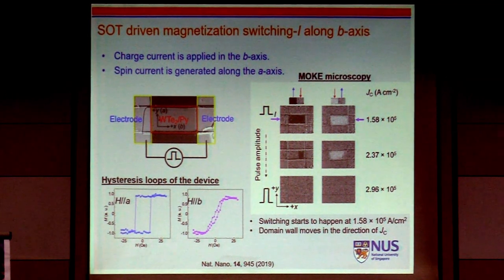And this material is very anisotropic. Depending on the current injection direction, whether you are injecting along the A or B, you can see quite different behaviors. This is an example with current along the B direction, and then we can polarize our spin along the A direction. This is the initial magnetization direction. As we increase the current, we switch from black to white. Starting from white, we can also switch back.